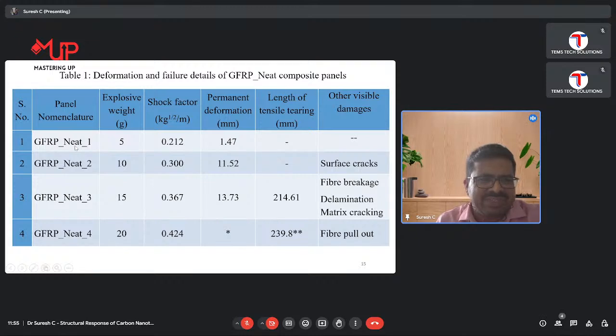So we studied the plain GFRP composites. We used different weights of explosives, like 5 gram, 10 gram, 15 gram, and 20 gram. And as I told, the shock factor. For 5, 10, 15, and 20 gram, we have calculated the shock factor, and we kept the distance 150 mm as constant for all the tests. And we have measured after the test what is the permanent deformation.